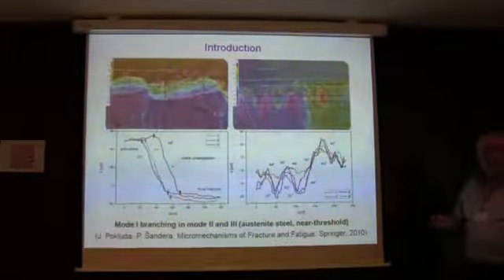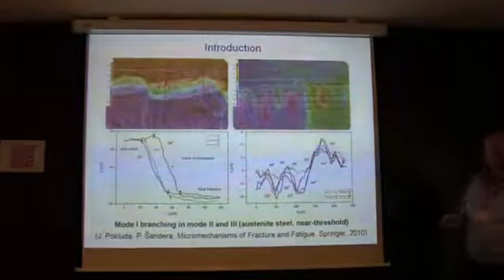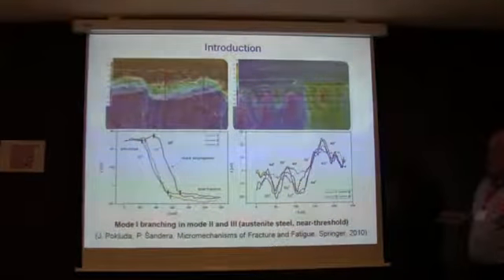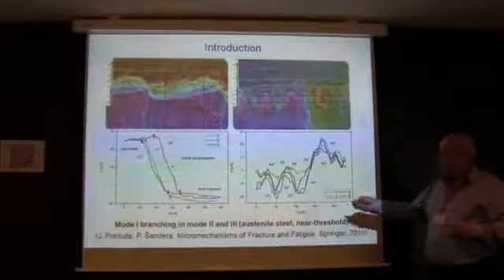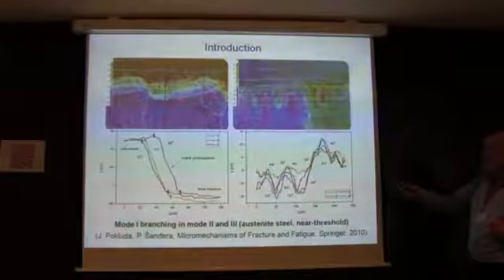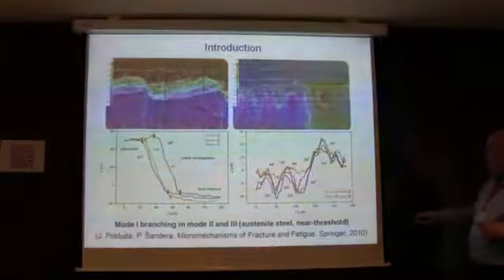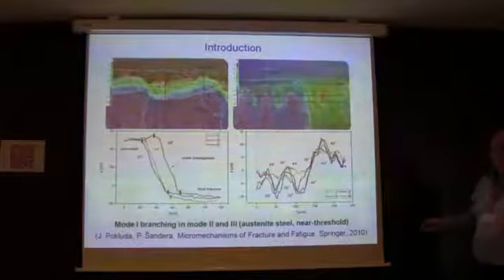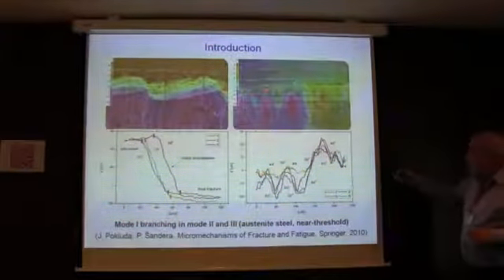The theoretical value of the branch is 70, and you get a really mode 1 branch. So this is very close to this value of 70. This is really mode 1 branch in mode 2. This is in an austenitic steel, near threshold. And this is the mode 3 case. You see the profile like this.